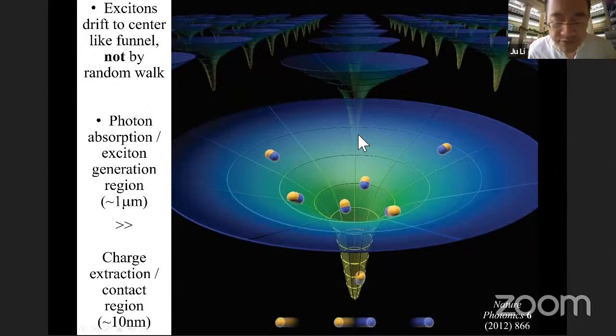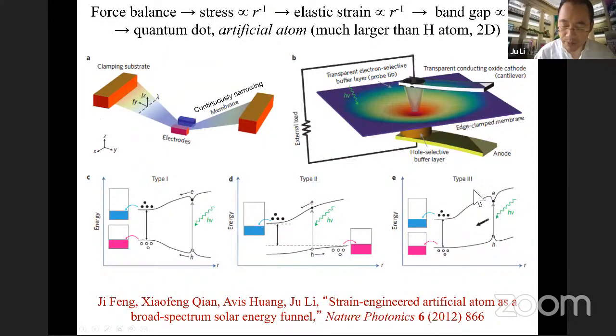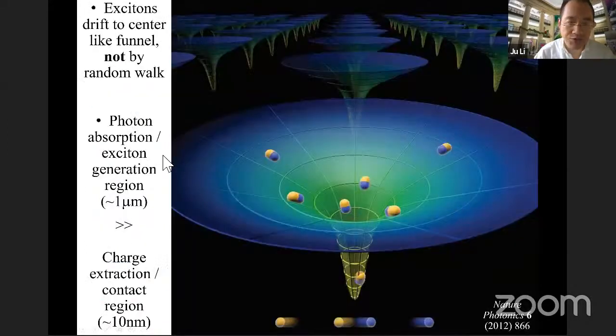And that will be quite different from the standard photovoltaic materials, because in standard photovoltaics, you have this electron hole pair, and they would undergo random walk by tens of nanometers until they hit an interface with a built-in field that can separate the electron from the hole. But in this case, because you have this band gap gradient, you can actually induce drift of this charge neutral exciton. And when we put in the numbers, we predicted that this exciton can drift by microns. And so you can have micron-sized 2D material as a solar energy absorber, but you only need to separate the charge at the origin of this artificial atom.